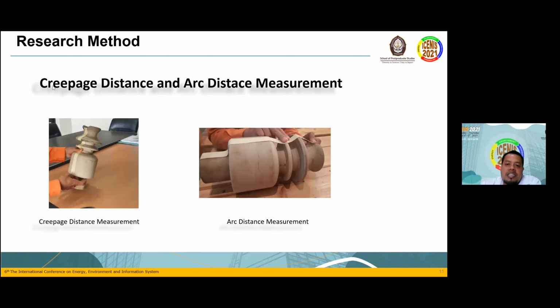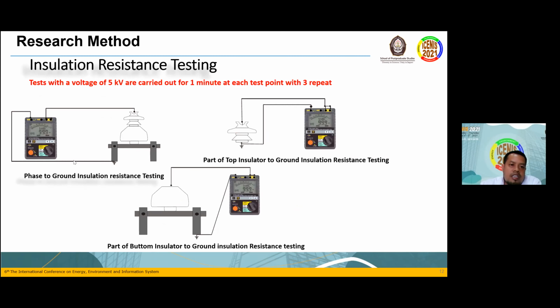Creepage and arc distance measurement. This figure shows the method of creepage distance measurement, and this figure shows the method of arc distance measurement. And insulation resistance testing. The test with a voltage of 5 kV is carried out for 1 minute at each test point with 3 repeats. Phase to ground insulation resistance testing, top part of insulator to ground insulation resistance testing, and bottom part to ground insulation resistance testing.